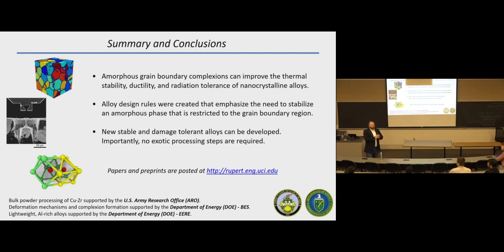So until now, we've been working in the range of 1 to, I would say, the average even in the aluminum is 5 nanometers, with some outliers that are 9 nanometers thick. In that range, you're still getting a benefit from increasing the thickness of the amorphous films. So you certainly would run into it if you kept going. I'm not sure you can get much thicker than that and have those stable films. So within that range of a few nanometers, thicker is better.